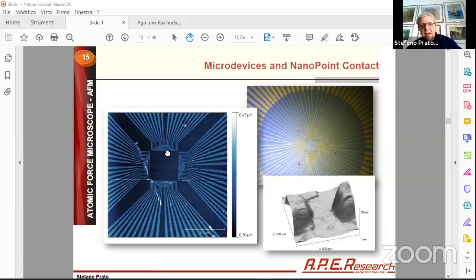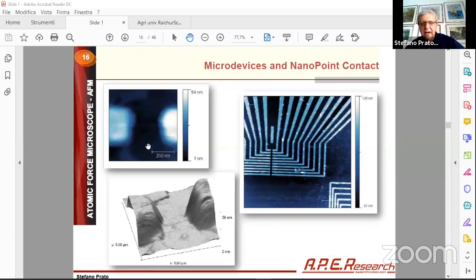So with AFM, you can really zoom down to this size, as I show you here. You watch first the sample with the optical microscope, then you do a large area with AFM, then you do a slightly smaller area, and then you zoom down to, this is 400 by 400 nanometer size. This is the same image in a 3D mapping. So if you put some molecule in the middle of here, you can measure some electrical property, for example, if you want to develop some nanosensor and so on. But okay, this is more general, depending on the research field application.